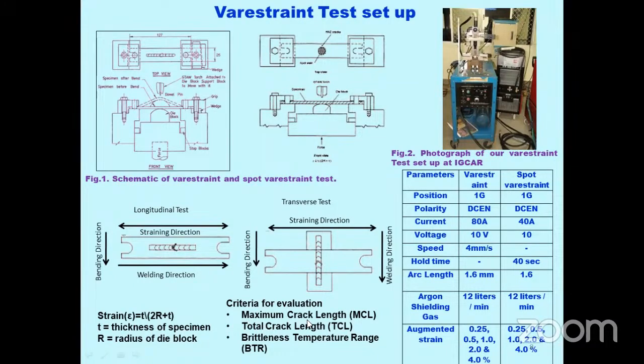Maximum crack length is measured from the surface of the fusion zone of the tested specimen. We have some cracks forming on this specimen, and the length of the maximum crack formed on the weld metal is used as a criterion for evaluation. One more parameter is the total crack length. We calculate the sum of all the cracks formed on the surface along the weld fusion line. And for the brittle temperature range, there is a separate module to determine it for this experiment. Some parameters that we use during the Varestraint experiment are shown here.